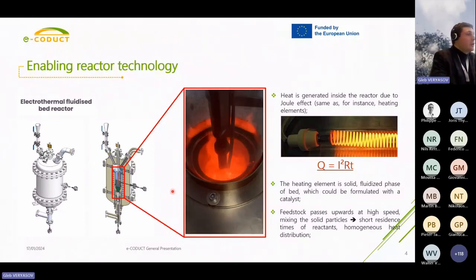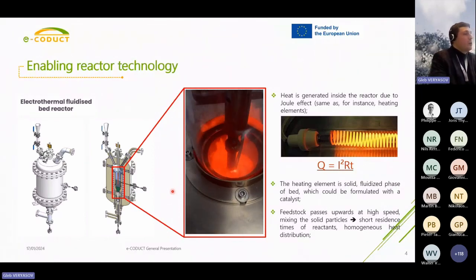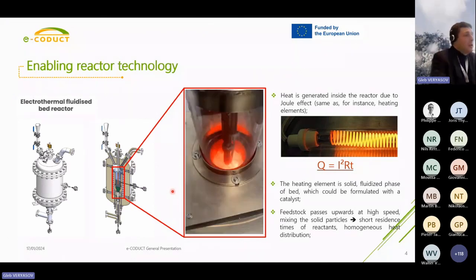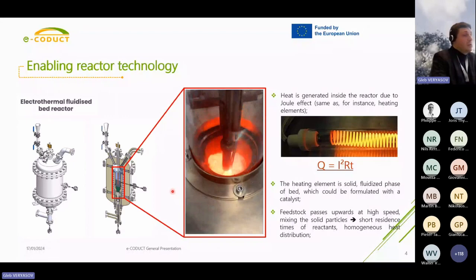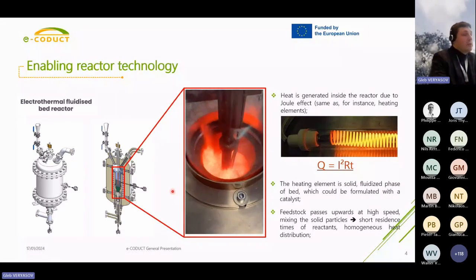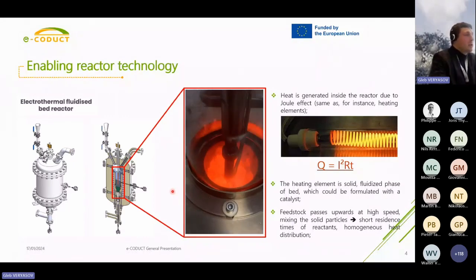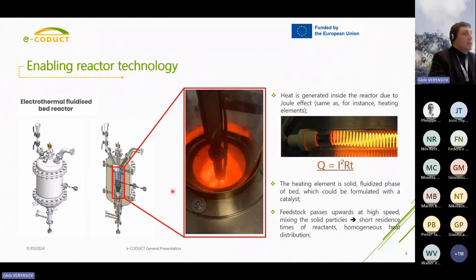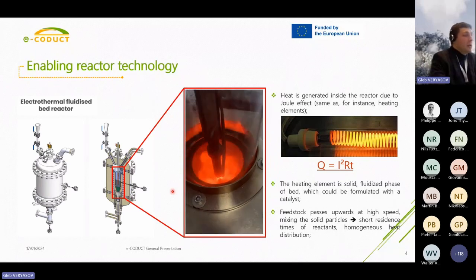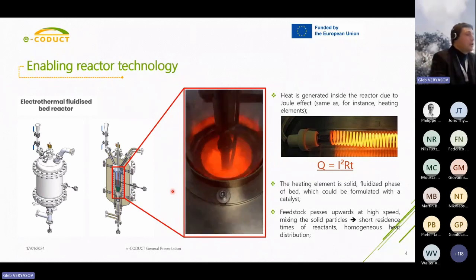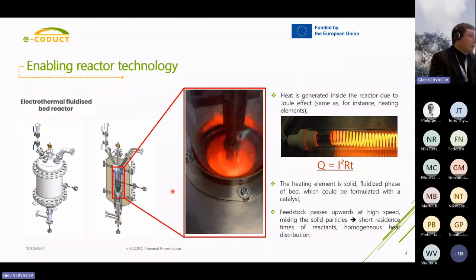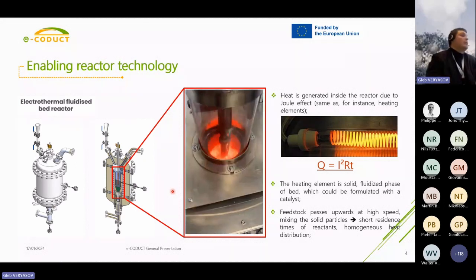The feedstock in our case is going upwards, and the gas is creating this fluidization, which has a double function. First, it contributes to resistivity, so it's an important factor to create heating inside the catalyst bed, and also it allows us to reach short residence times and homogeneous heat distribution inside the reactor.